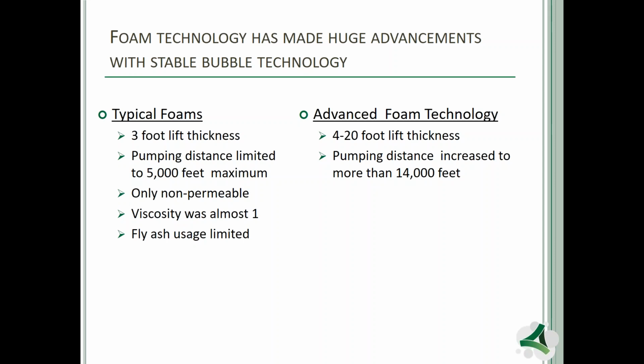We have now pumped this material for over 14,000 feet. We just had an installer in Hawaii work on a tunnel that I'll share with you in a little bit that pumped the material just shy of 3 miles, just over 15,000 feet. So if you think about that, when taking the material through a 3-inch or 4-inch hose and pumping it for distances, you can offset your batch mixing equipment at a distance and then lead into the job site with a 3 or 4-inch hose and eliminate a lot of safety aspects within the job site and remove a lot of traffic away from the job site as well.